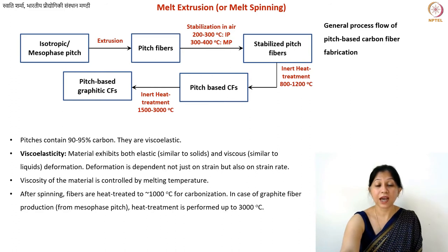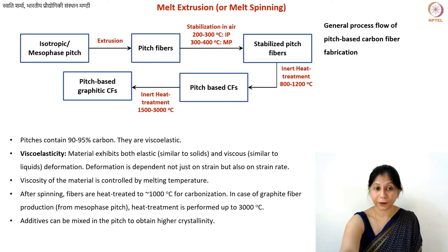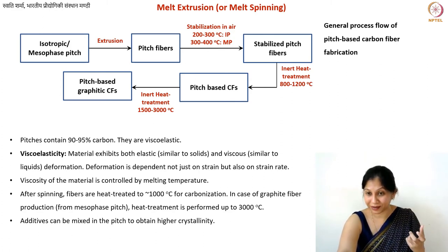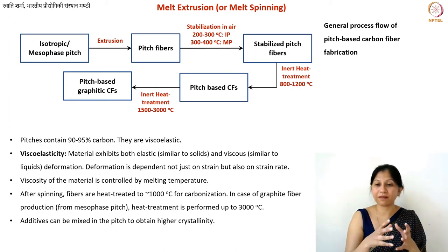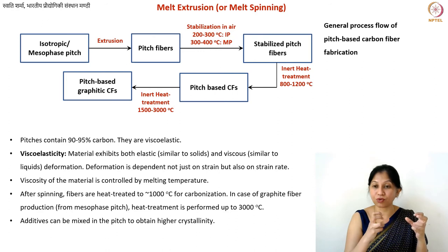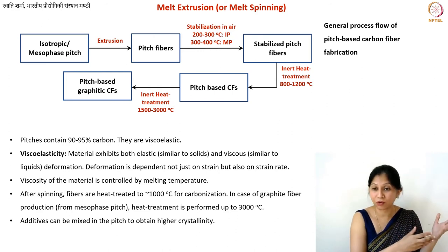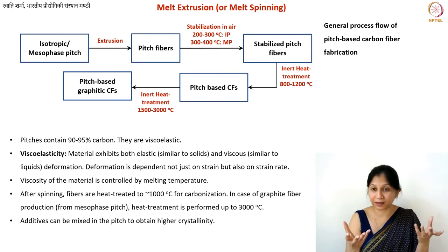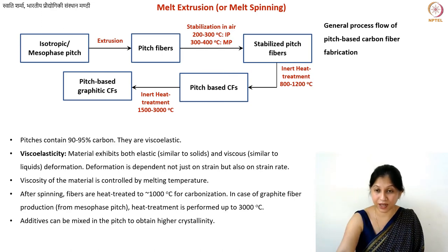For pitch, viscosity is controlled by controlling the melting temperature. Heat treatment is then performed under inert environment after the stabilization step. You can also add certain co-particles or carbon nanomaterials such as carbon nanotubes as additives to isotropic pitch to improve crystallinity. However, the concentration and size of the additive must be optimized — too large and the particles will block the capillaries in the spinneret.